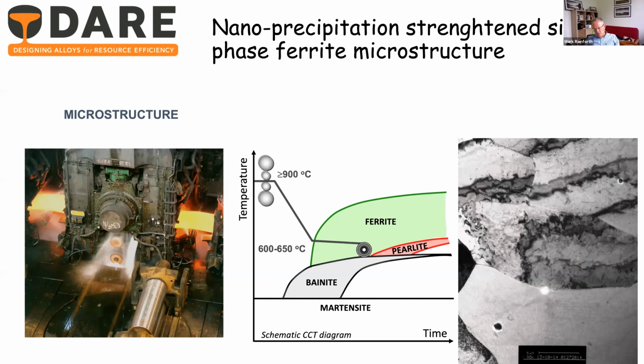As I say, to develop this, there's lots of good academics that sit in their laboratories developing new materials, but then can't be scaled up and can't be used in plant or need major new investment in plant. The remit here was very much to be able to manufacture within the existing plant. So that involved rolling, finish of rolling was about 900, and then a rapid cool to the coiling temperature where it would be held somewhere in the range of 600 to 650 degrees centigrade, at which we'd get transformation into the ferrite. But the key was to achieve this interface precipitation.